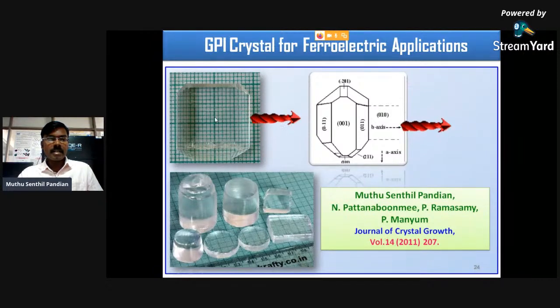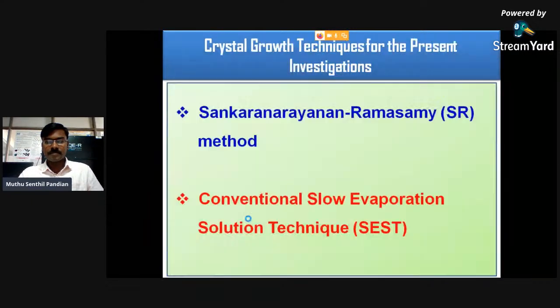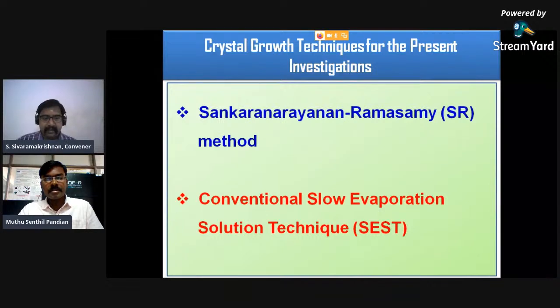This is again glycine phosphite, GPI, single crystal for ferroelectric application. We have selected this polar b axis for ferroelectric application. We have mounted it at the bottom of the glass sample, and we have grown the crystal along its polar b axis. This is the SR method grown, cut and polished GPI single crystal. So the crystal growth techniques for the present investigation I am going to explain is this conventional slow evaporation method.